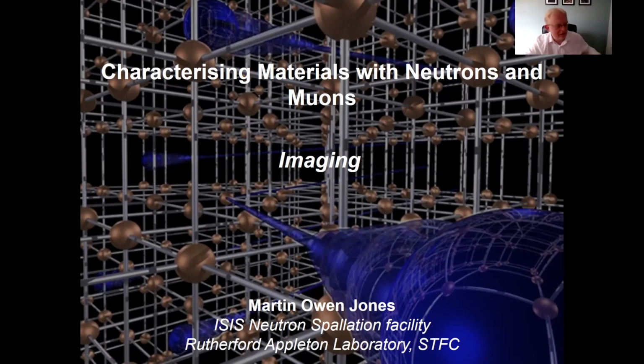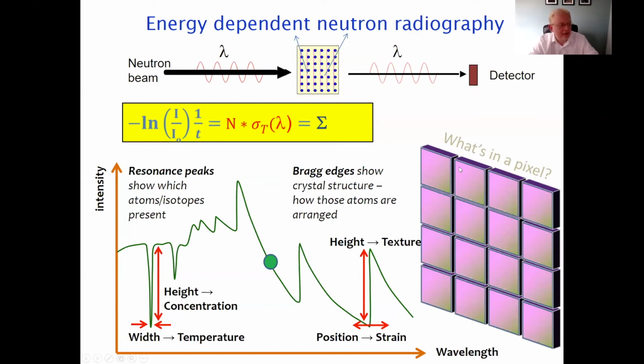So one of our rapidly developing areas is imaging with neutrons. And the new IMAT facility that we have allows us to look at and create images of materials in a sort of tens of micron resolution range. And not only will that give you a tomography image, like a three-dimensional photograph of your material, you can also extract information on the texture. So look at the Bragg edges, which will tell you how the atoms are arranged within the structure, and look at the Bragg resonance peaks, which tells you which atoms or isotopes are present.